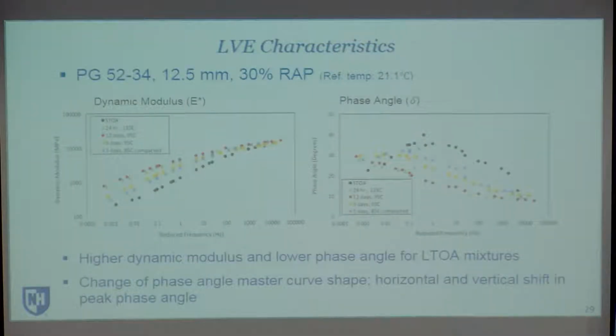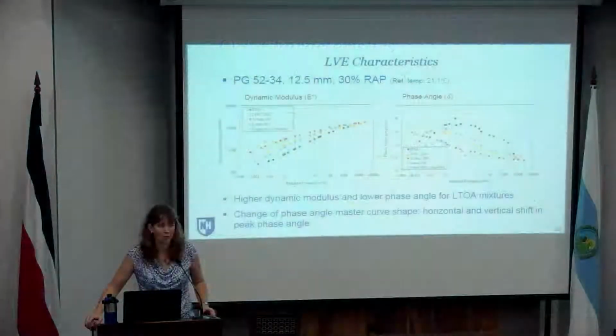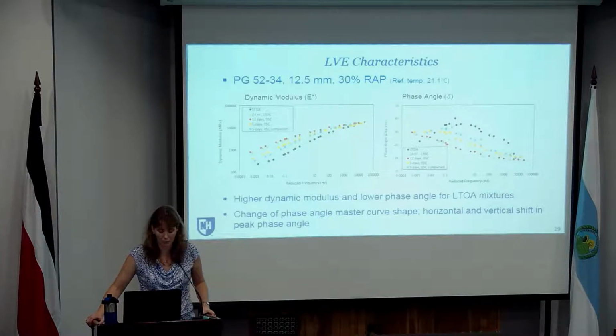So I'm going to go through some sample plots here, and these are for one representative mix. I'm not going to show you the results from all of the mixes because the general conclusions and the general trends that we saw for all the mixtures were very similar. So the data that you're going to see is from one of the PG 52-34 mixtures. It was a 12.5 millimeter, 30% RAP. So you can see here in these plots, we've got the dynamic modulus and the phase angle master curves. And you can see the short-term age. So again, these are all plant-produced mixtures. I should say these are not laboratory-produced mixtures. For this part of the project, it was all plant-produced mixtures.